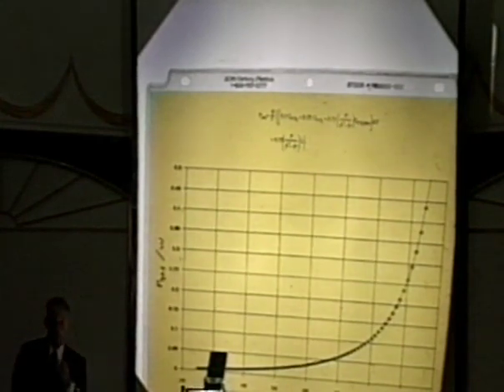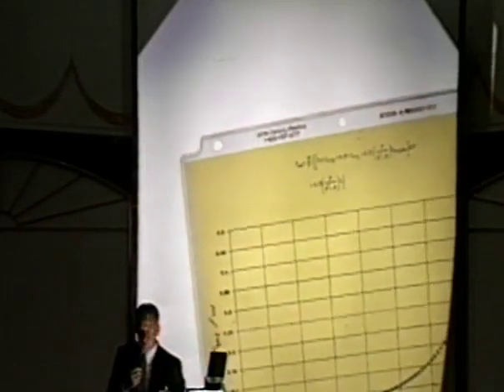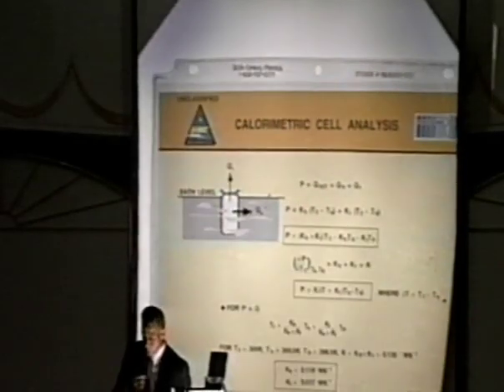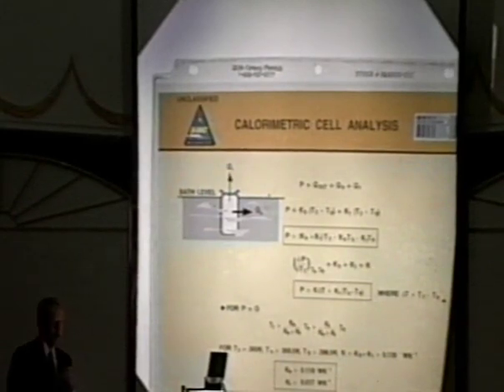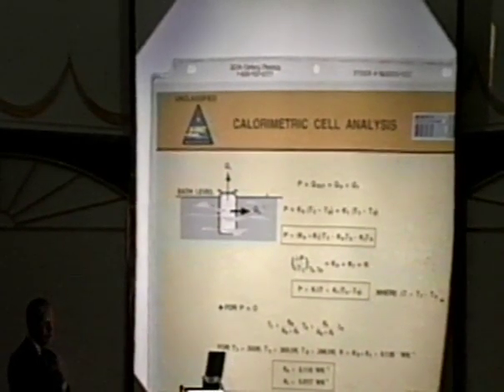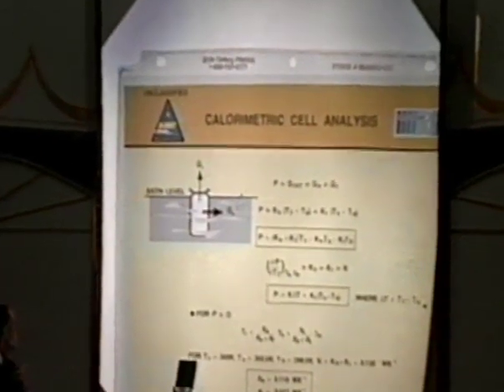So of all these terms, that last term involving the L is the largest term because that involves the evaporation of D2O from a liquid to a gas, and that becomes the major term in that equation. So you have to consider these full equations, especially if you're working at high temperatures, as you get up above 60 degrees. And in addition, you need to be concerned about, in our case, the heat carried away through the top of the cell to the room temperature. The room temperature does play a big effect. And our major improvement recently is we have a secondary box over the top of the cell to keep the temperature at the top of the cell more constant, because that's a big error. If the room temperature changes 1 degree, that can produce a big error in your results.